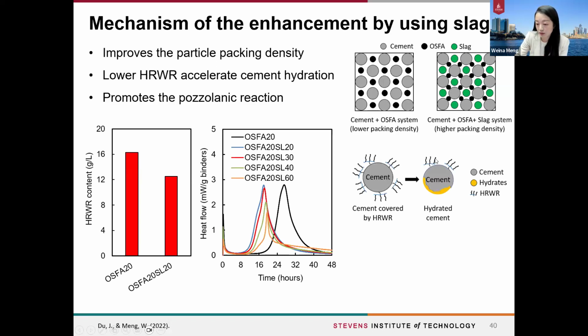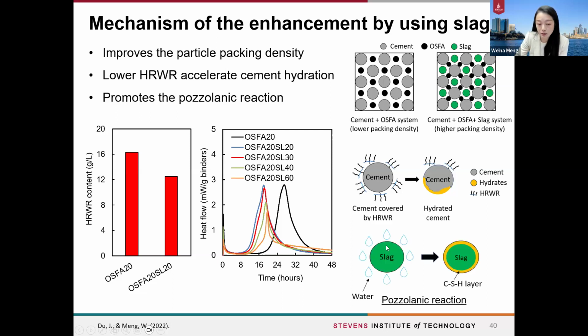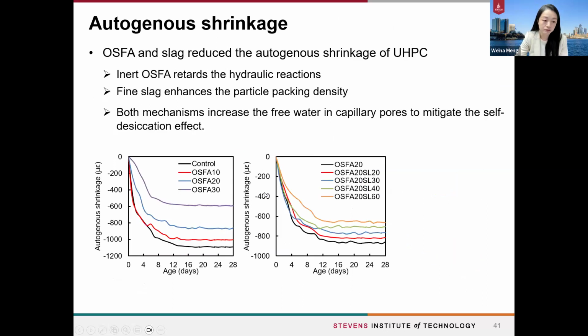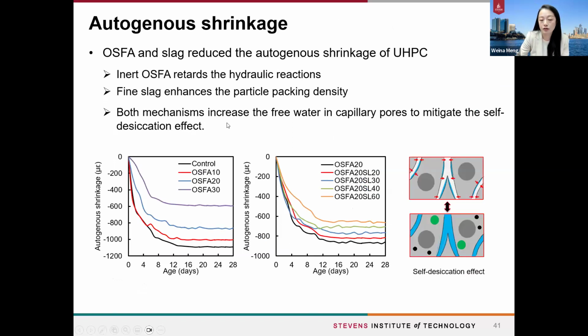So it's basically a long chain polymer. So we can expose more cement to the water for the cement hydration. And also, as the slag is a pozzolanic material, it will promote the pozzolanic reaction and form more dense and strong hydration products. And also both the OSFA and the slag show benefits in reducing autogenous shrinkage. Basically, both of them could release or increase the free water in the system and in the capillary pores, so that we can mitigate the self-desiccation induced shrinkage significantly.